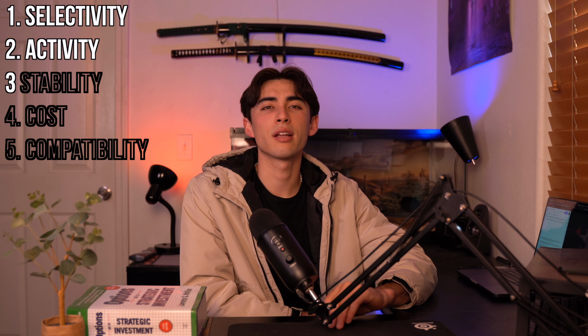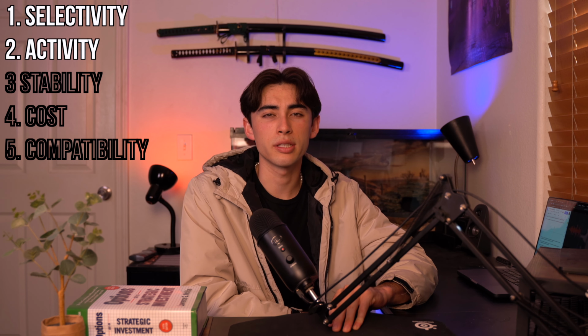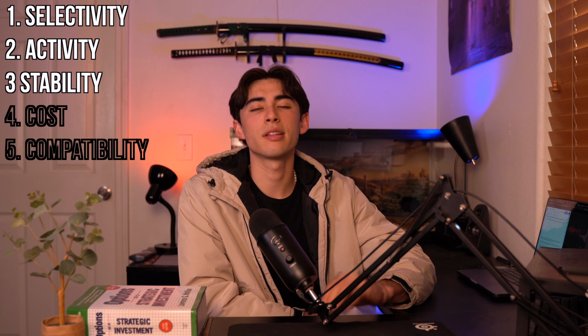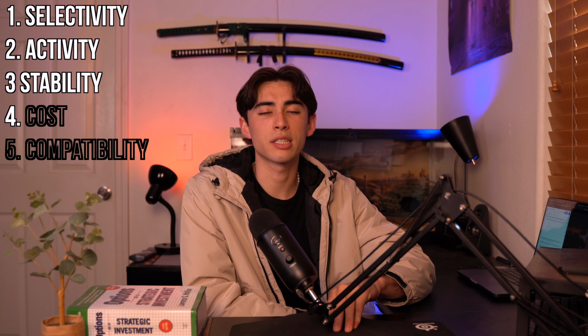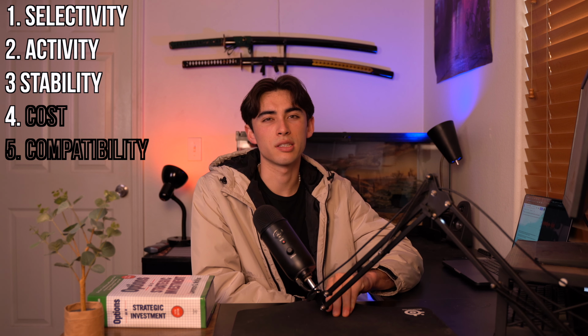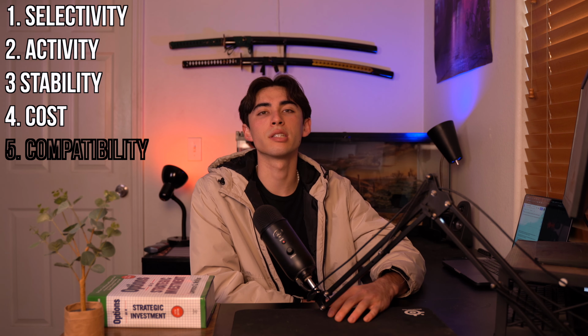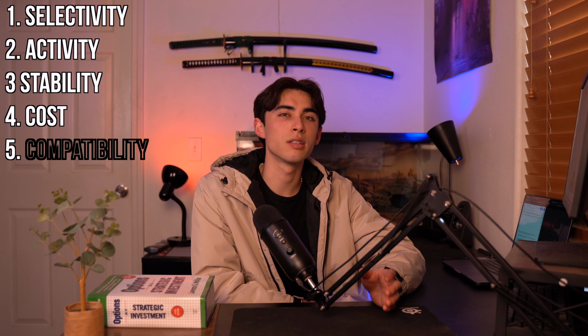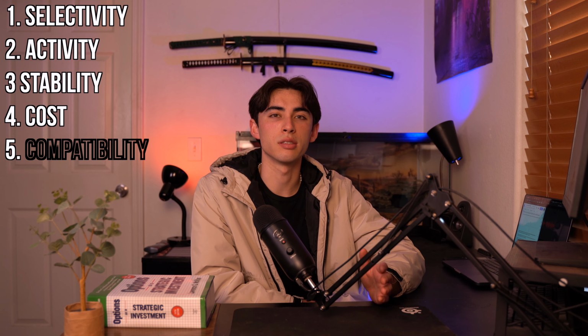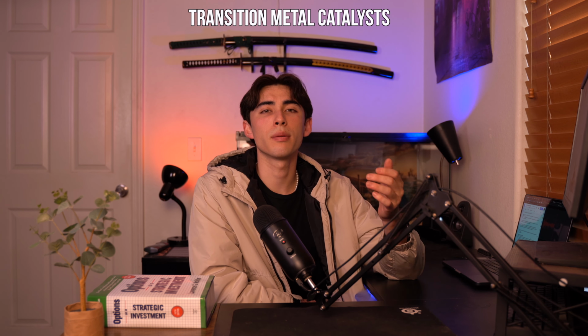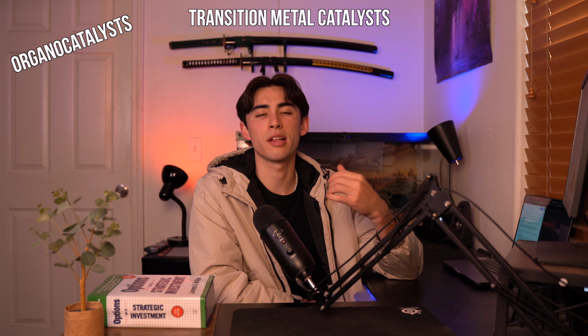Number 2 is that the catalyst should have a high activity, allowing the bond exchange reaction to occur at reasonable rates under mild conditions. Number 3 is that the catalyst should remain stable under normal reaction conditions, not degrading or deactivating at any time. The fourth consideration is the cost of the catalyst, which should be heavily considered, especially if large-scale production is intended. Finally, the catalyst should be compatible with any other areas of the CAN, including the polymer backbone and any additives. Many different types of catalysts can be used for CANs, but the typical choices are transition metal catalysts, organocatalysts, and enzyme catalysts.